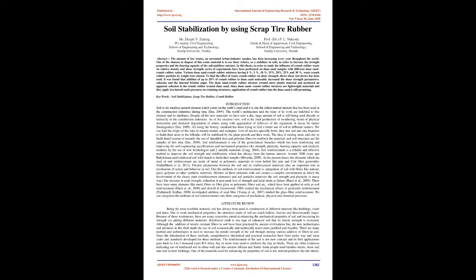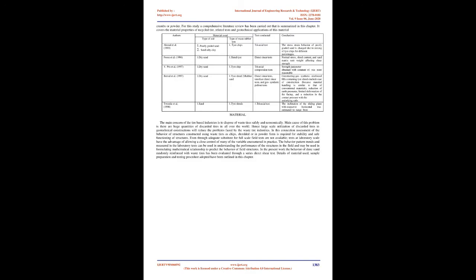It was found that addition of up to 20% of crumb rubber to dune sand noticeably increased the shear strength parameters, cohesion and the internal friction angle. The dune sand crumb rubber mixture created more plastic material and produced an apparent cohesion in the crumb rubber treated dune sand. Since dune sand crumb rubber mixtures are lightweight materials and they apply less lateral earth pressures on retaining structures, application of crumb rubber into the dune sand is still promising. Keywords: soil stabilization, scrap tire rubber, crumb rubber.